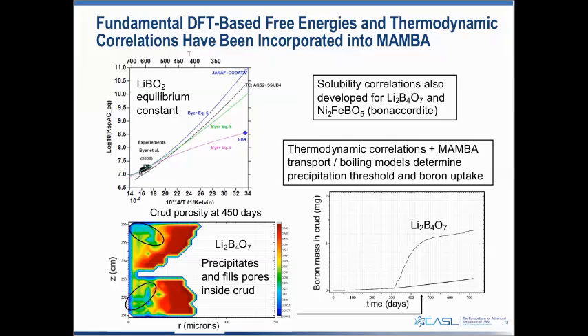Over on the right, it shows an integrated boron mass as a function of cycle time. As the crud layer gets thick enough, it heats up, eventually you reach the solubility threshold, and suddenly lithium tetraborate starts to fill the pores of the crud layer.